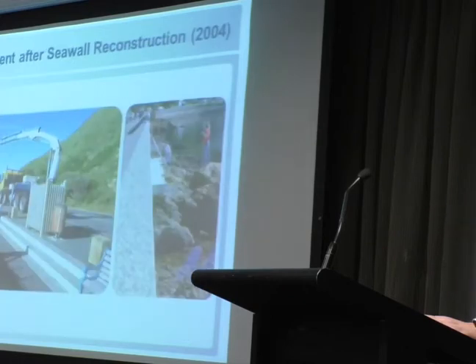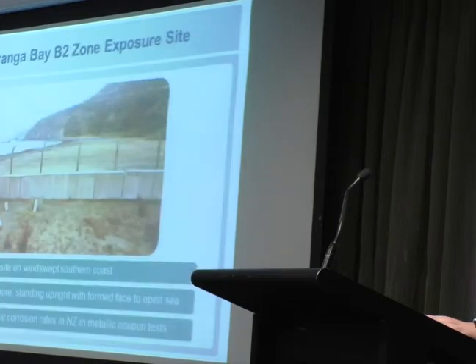And this is one of the problems. The program went on for 5 years initially, and halfway through the program, the council decided that they wanted to redevelop that area of the waterfront, so the blocks had to be removed and subsequently replaced on a new purpose-made platform. And this is the B2 site, so this is for blocks where chloride exposure is by windblown aerosol, about 100 metres from the high tide.